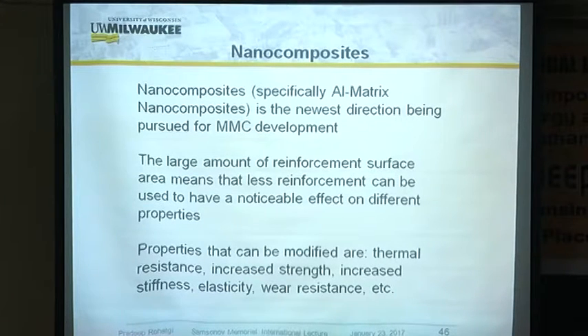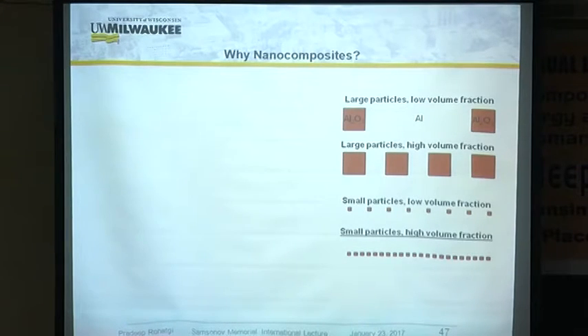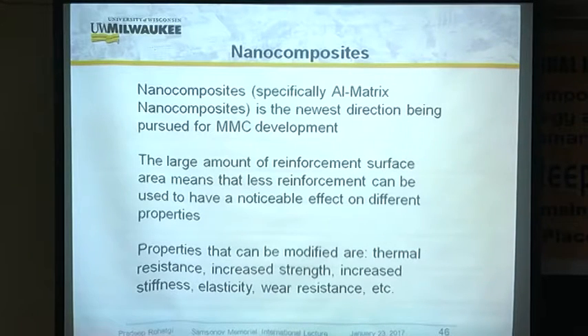I did mention why am I getting into nanocomposites, because the reinforcements are much stronger. Graphene has a strength and modulus in terapascal. So if I can put it in metals, I can produce really strong material. So nanocomposites are a very exciting field, and we have gotten into nanocomposites. I'm not going to get into the mechanisms of strengthening, which include Orowan strengthening, Hall-Petch strengthening, CTE mismatch strengthening, load transfer. These are all standard textbooks.